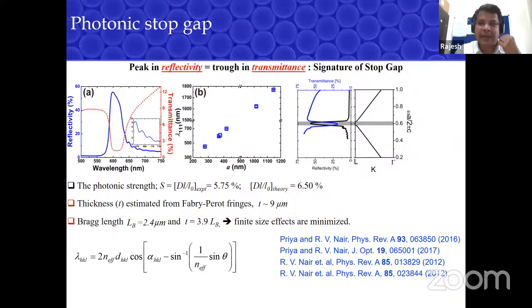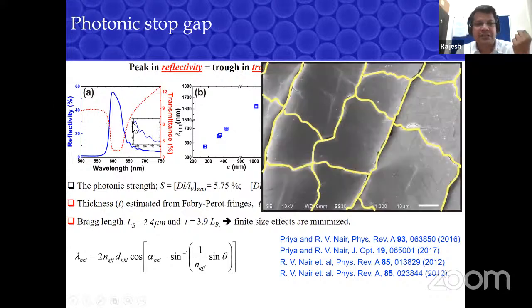So we look at the sample, and the reason is that when we do this kind of measurement, we use a light beam of the order of 5 millimeter on your sample. That means it is actually mapping all these dirty things in the sample, all these cracks, all these point defects. So the light is reflecting in all directions. Now the question is, can we measure from this small region, which is just 100 by 100 micron or even less than that?